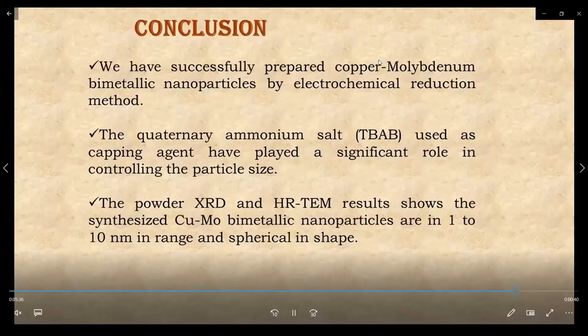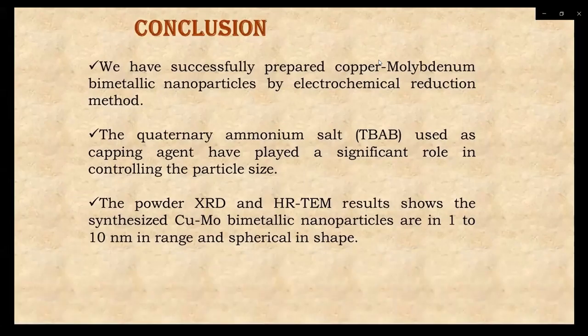Lastly, we conclude that we have successfully prepared copper molybdenum nanoparticles by the electrochemical reduction method. The quaternary ammonium salt, that is tetrabutyl ammonium bromide, used as capping agent, has played a significant role in controlling the particle size. The powder XRD and HRTEM results show the synthesized copper molybdenum bimetallic nanoparticles are in 1 to 10 nanometer range and spherical in shape.